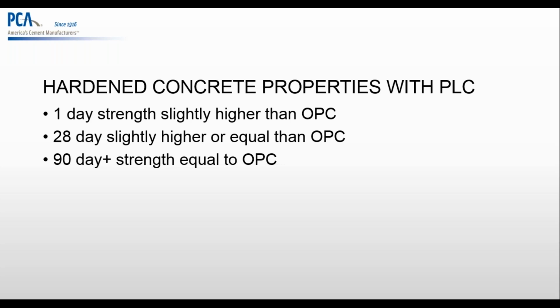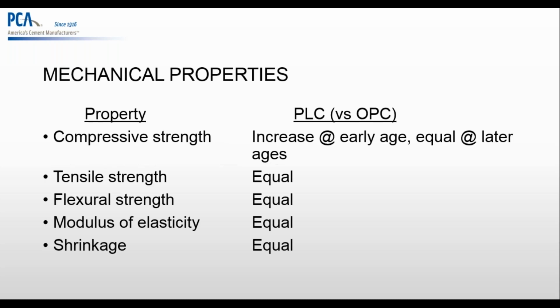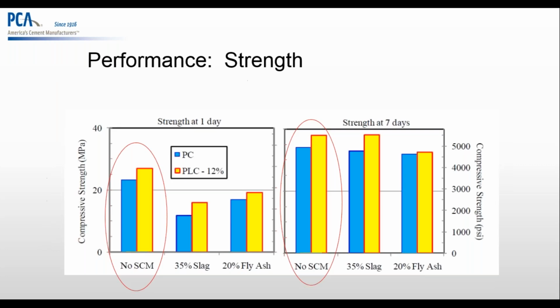As far as the hardened concrete properties, what we've seen, at least here in Florida, is that it's pretty much the same. Some people have seen a slight increase in strength at 1 day and at 28 days, and pretty much equal at 90 days. Again, the mechanical properties, tensile strength, flexural strength, modulus of elasticity, and the shrinkage are pretty much equal. And that's exactly what we want. That's what we're looking for.